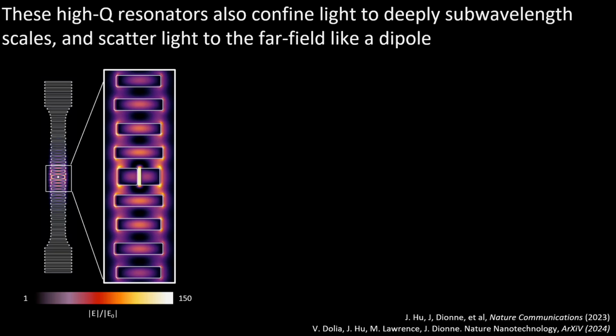And you can see how this is acting almost like a lens to focus light to the nanoscale. In this case, apologies for not including a scale bar on here, but here we have extreme mode confinement. Each of these bars is just about 200 nanometers across. So basically the mode volume is about 10 or so nanometers cubed, so extremely intense electromagnetic fields in a very small mode volume, but in this case using silicon.